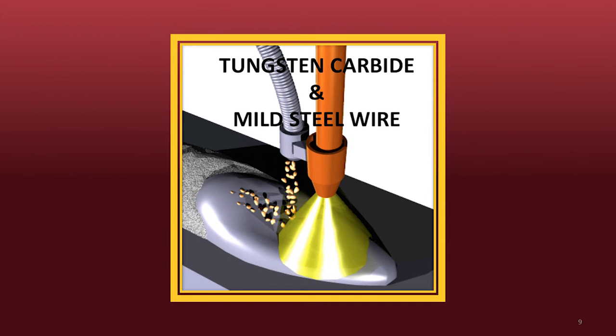Let's review the prior use of tungsten carbide hard banding. In the age of shallow and straight wells without casing, it was common to apply mild steel wire together with tungsten carbide particles. The particles are carefully metered into the weld puddle, but not the arc. This process was used extensively until deeper and horizontal wells came about in the last few years, as we shall see in a later slide. These types of hard bandings had catastrophic consequences within cased holes. The newer and harsher drilling conditions call for more casing-friendly products such as DuraBand.